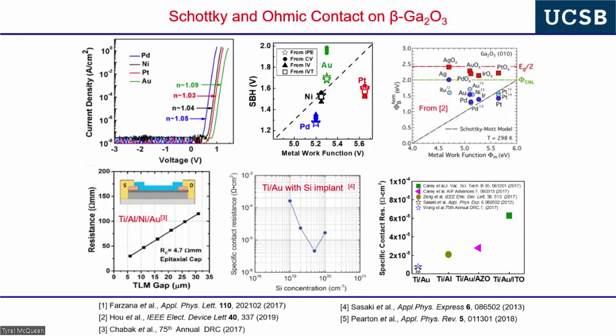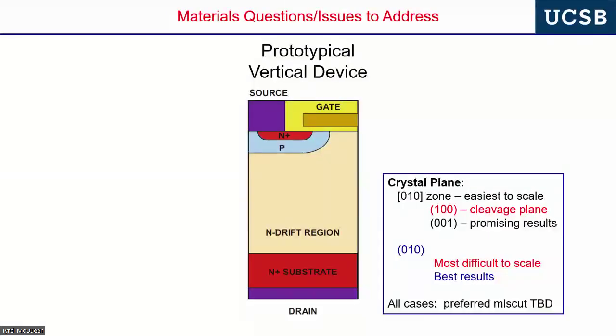There's a wide range of Schottky barrier heights to work with, and I'll talk to you about some of the work that we're doing in our group on increasing the Schottky barrier height or decreasing the effective Schottky barrier height, okay? And then either with implantation or just using low work function metals with beta gallium oxide, we can get outstanding ohmic contacts. So very early in the field, we had outstanding contacts, both Schottky and ohmic contacts. And this was really a very pleasant surprise, particularly for folks who had never seen this because they'd already worked on defective semiconductors, and they always get very, very leaky diodes. And so that's been a very pleasant surprise.